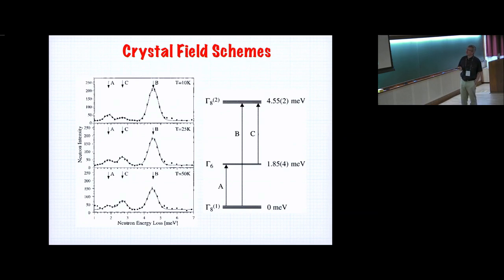And so in neutron scattering, here's some data to a first approximation to get the energy scales. All you have to do is fit the resolution peaks and then understand its temperature dependence, and Q dependence, and you pick up things. But you see the B here is the transition from the ground state to this second set of crystal field levels.